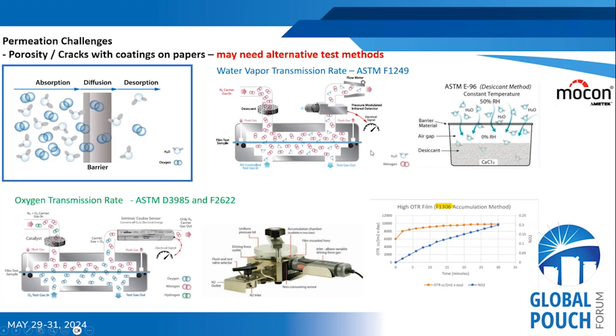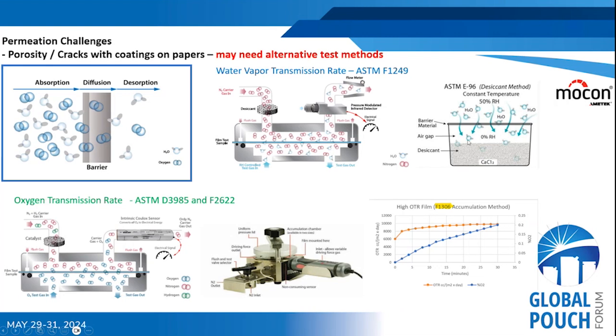So what we look at sometimes, if we're given films like this, where we can have flow issues or things like that, where water can actually go through very, very fast and the coatings aren't very good, we'll use an older, more traditional test called ASTM E96. This is a gravimetric test. We take that coated paper and attach it to what we call a cup, a vessel that holds desiccant. We put that cup inside a chamber with a controlled humidity. It could be 50% RH, could be 90% RH, whatever we want it to be as long as we're controlling it. And 50% RH is actually very common for papers.